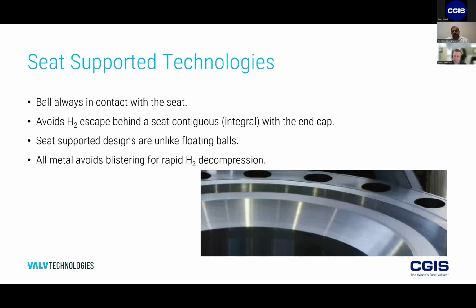The other thing that's got to be considered too is the materials of construction. One of the disadvantages of soft-seated valves is that if they have any rubber components, and for whatever reason a rapid decompression was to occur, when hydrogen escapes rapidly or decompresses, rubber materials have the risk of blistering. If they blister, then it only progressively gets worse. And so that's why a metal-seated design, although metal-seated designs are typically associated with higher temperatures, and most hydrogen applications are pretty much at ambient, not very high temperatures, the metal-seated design is really intended for the avoidance of rubber components if there was to be a decompression event.